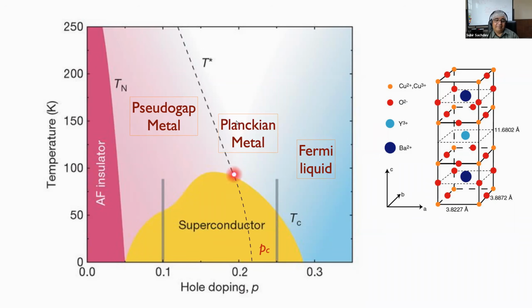And finally, in between, we have a strange metal, or now being called a Planckian metal, where the characteristic time is independent of the strength of the interaction and just given by temperature itself. Okay, and this Planckian metal seems to be associated with some critical doping, PC, which is now being determined by various methods fairly accurately in many compounds. So roughly speaking, the scenario we have is you have some pseudogap metal where the Luttinger theorem is violated, a Fermi liquid where it is not, and then some quantum critical point near PC, which determines this Planckian metal physics. Okay, so my focus will be entirely on these three different metals.